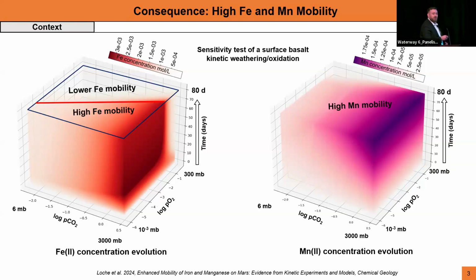The more red, the higher the concentration. And you see that iron is very mobile, even at very high partial pressure of oxygen. And for manganese, it's even worse. It's always mobile, basically, even at partial pressures of oxygen that are higher than on Earth.